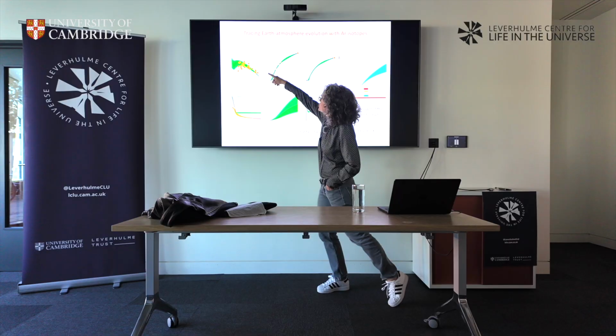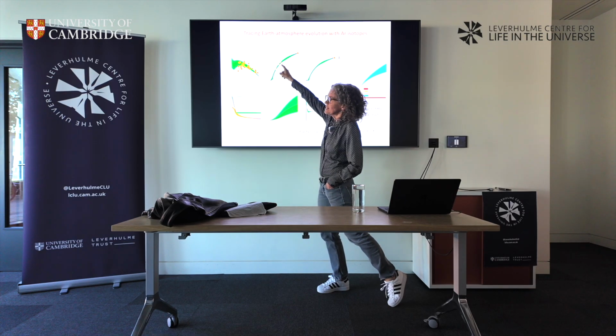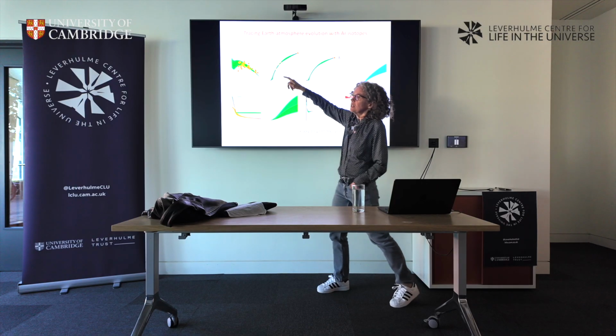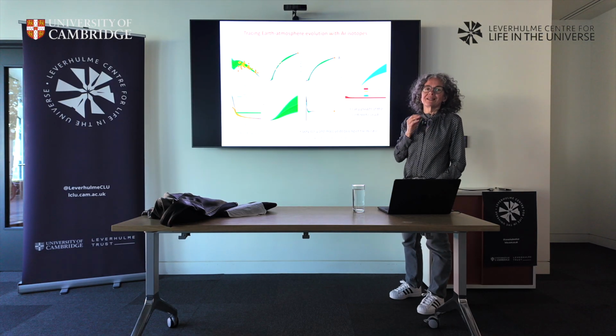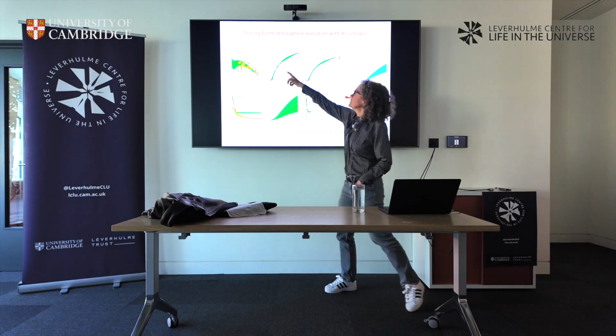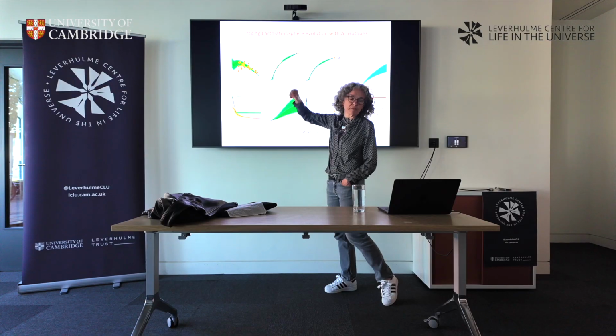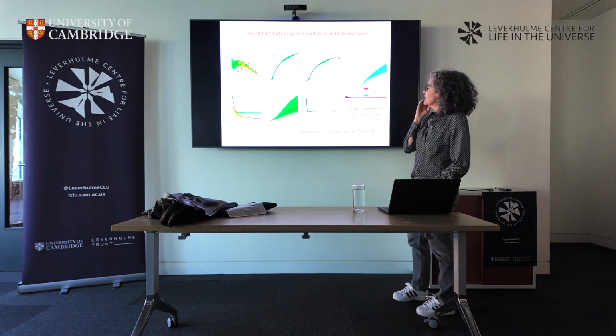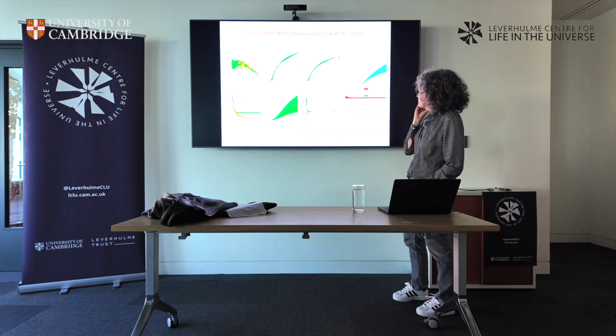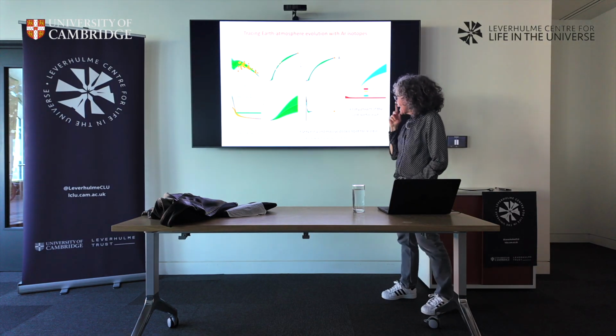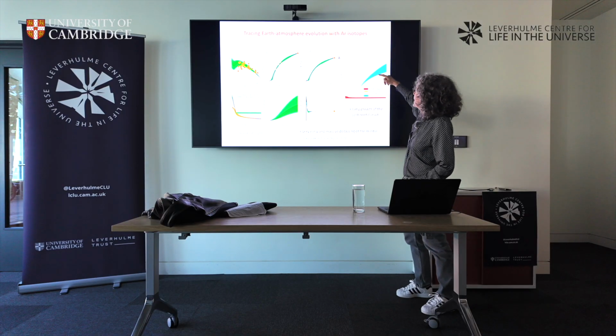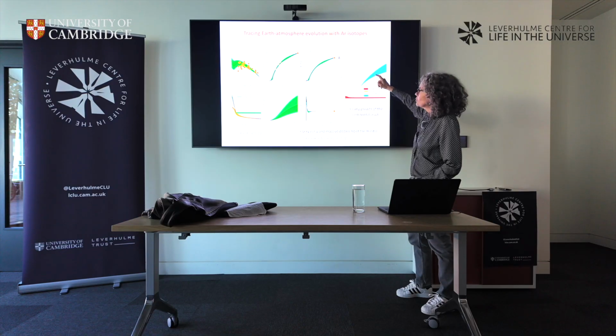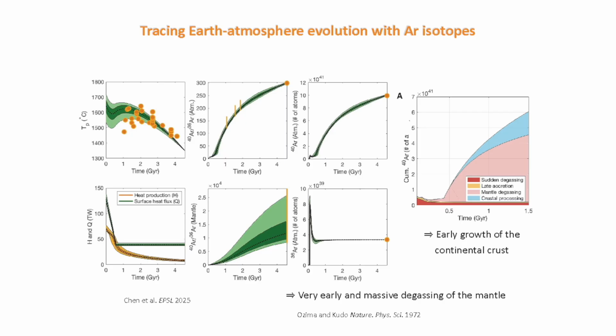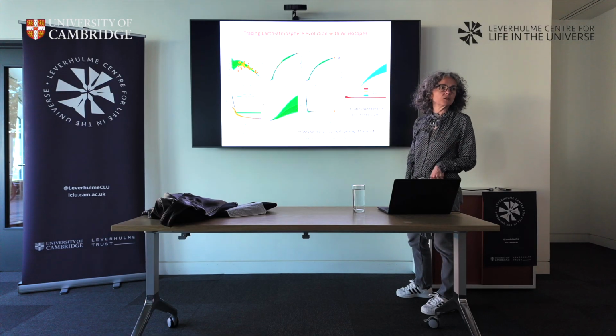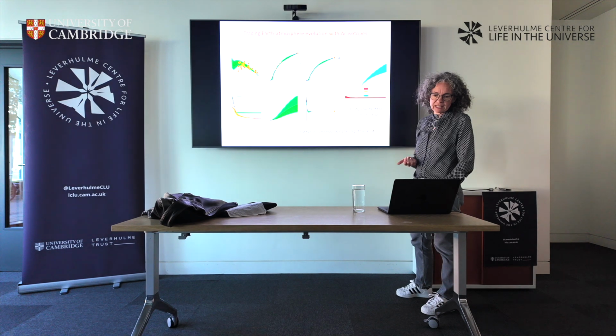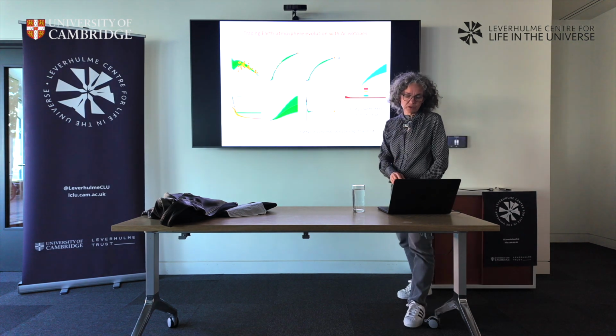So this is measurements of argon isotopes in fluid inclusions in quartz that are interpreted as paleoatmosphere. It's very difficult to date. So it's only one data point, but they are not sure of the age, hence the 3 points, as far as I understand. So they try to fit that, and the conclusion is that you have a very early massive degassing of the mantle. The other conclusion is that to explain the amount of argon-40, mantle degassing is not enough. You need to have the continental crust kicking in. Otherwise, you miss something. So: very early massive degassing of the mantle and very early growth of the continental crust.